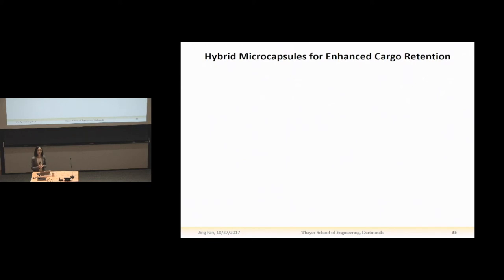So if we want to encapsulate it in a hydrophobic shell using a double emulsion, then we need a hydrophobic oil as the middle phase, but then the encapsulated cargo, which is hydrophobic, won't work. We couldn't have oil as both the inner core and the middle phase. So we came up with the idea to use a triple emulsion. We have a hydrophobic core and then an aqueous solution shell, and then encapsulated by another hydrophobic shell again. And this three-layered droplet will be suspended in water again.